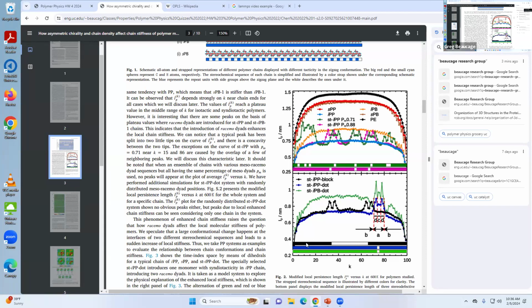But basically, there's no way to do that with tacticity. You'd have to have either anionic, cationic, or RAFT polymerization going on, and then you'd have to be able to change the catalyst that was running the polymerization. So replace Ziegler-Natta with some other catalyst that doesn't exist. Or maybe there is. Let's see, the iso and syndio, in some polymerizations, you can change just by changing the temperature of the reaction. Like if you run this one at minus 200 C or something, and then run it at room temperature, and then take it back to minus 200, that's possible, I guess. So it might be possible to do that, but basically no one's made block copolymers like that, I don't think. So that's what he means by block.